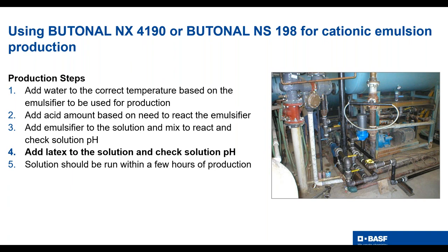Now, the production itself, the using of the latex and making asphalt emulsion. I'm going through some production steps here that are kind of the best practice that we're looking at. We typically add the water at the correct temperature based on the emulsifier to be used for production. So you want to get with your emulsifier manufacturer and they have a good idea. So basically you're putting the water in at that temperature. You're adding a little acid to the water and then usually add the emulsifier to react in that acid. The emulsifier is mixed around, you check the pH, and then you add the latex to the solution.